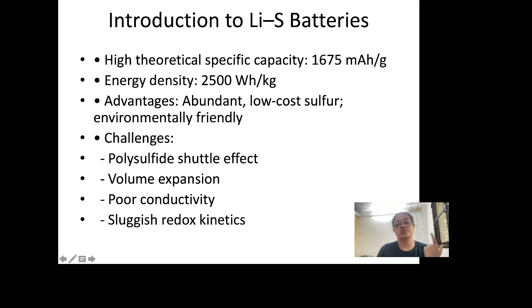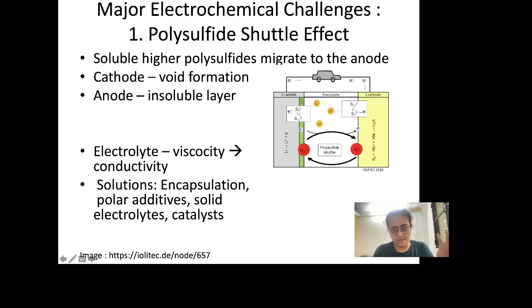So the main challenges include, firstly, the polysulfide shuttle effect. I'll get to what that is. Then second, which is something that happens with a lot of materials, a problem with volume expansion and contraction of the cathodes. Third is the fact that sulfur itself has poor conductivity. Fourth is that lithium and sulfur together, even though they have good electrochemical benchmarks, have slow or sluggish redox kinetics.